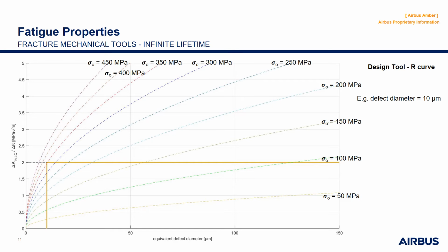So, a further tool for infinite lifetime is the so-called R curve with the threshold value for long cracks again. In this case, it is only an estimation, but will be elaborated by experimental data very soon and published afterwards. So one can estimate the endurance limit of the material by shifting the no crack growth region towards the observed defect size here. The intersection point with the respective stress isoplates will give us the endurance stress level. When, for example, observing the 100 megapascal endurance level, we saw defect sizes of approximately 10 micrometers, which fits very well with the estimated R curve.